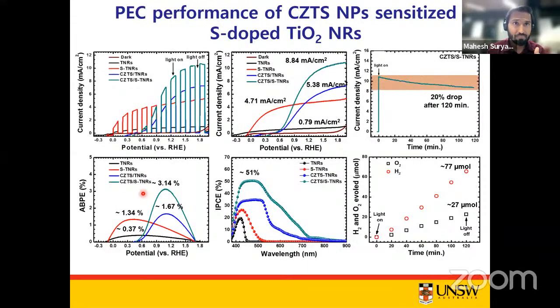We further measured the IPCE to find out the actual contribution of the sulfur doping as well as the CZTS sensitization on the TiO2 nanorod arrays. As can be seen from the IPCE, after sensitizing the CZTS on the TiO2 nanorod arrays, there is a substantial photoactivity over a broad range. This is the CZTS sensitized TiO2 nanorod arrays IPCE spectrum. You can see there is substantial photoactivity over a broad range from about 400 to about 700 nanometers. That suggests that after sensitizing the CZTS nanoparticles on the TiO2, there is an improvement in the visible light absorption.